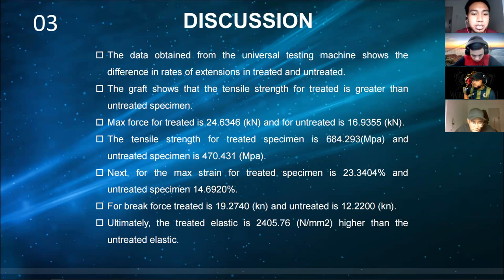So the tensile strength for the treated specimen is 684.293 MPa, and the untreated specimen is 470.431 MPa. Next, the max strain for the treated specimen is 23.340%, and the untreated specimen 14.6920%. For break force, treated is 19.2740 kN, and untreated is 12.2200 kN. Ultimately, the treated elastic modulus is 2405.76, higher than the untreated elastic modulus. Next.